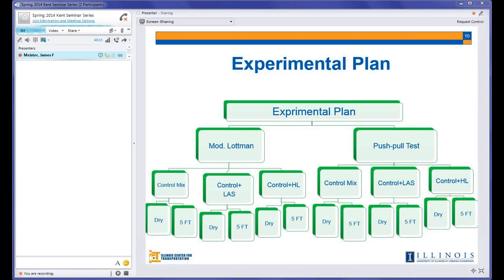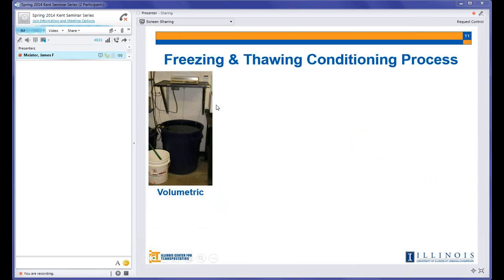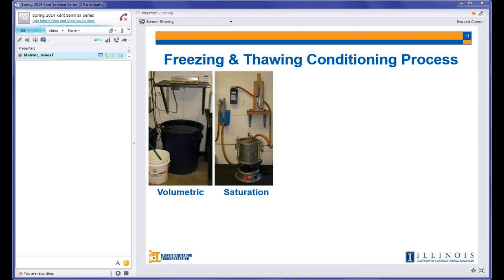And again, the condition was every time 5 freezing-thawing cycles. 5 freezing-thawing cycles, what does that mean in more detail? When we prepare the samples, we measure the volumetrics of each sample, meaning the amount of air voids in each sample. We saturate the sample by using a vacuum. Saturating here means filling 70 to 80% of the air voids of that sample with water.